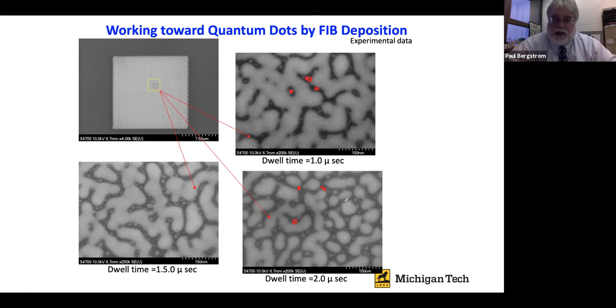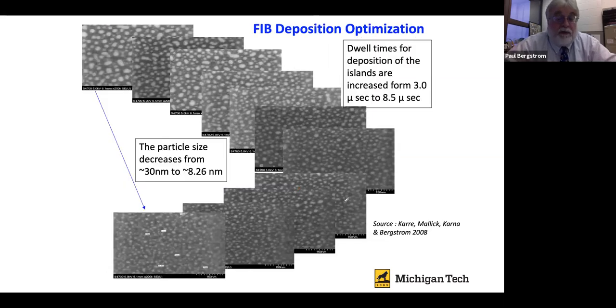So this is kind of how it started, but then through a very large series of experiments, I will say, we proceeded to pursue the different types of process conditions with the focused ion beam. This has to do with aperture size, energy of the beam, and the beam focus. We even did some defocusing of the beam. So beam focus, aperture size, dwell time, lots of things like that, in order to study how we get to a point where we can get feature sizes that are on the order of what we need.